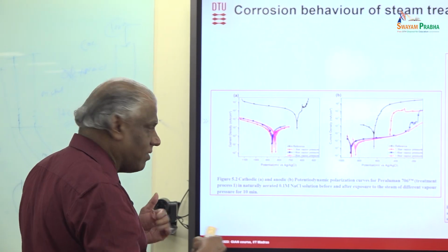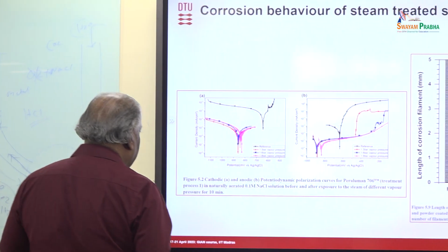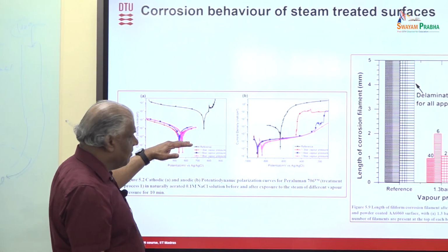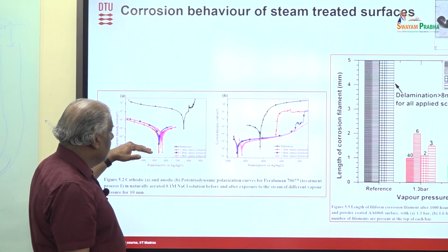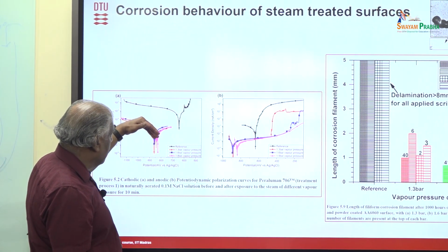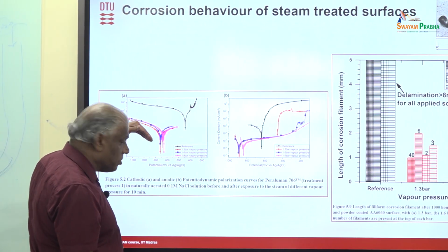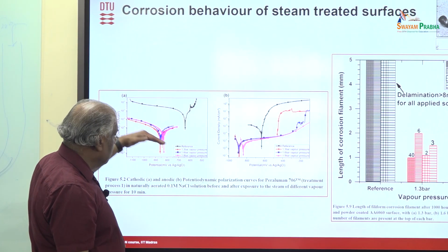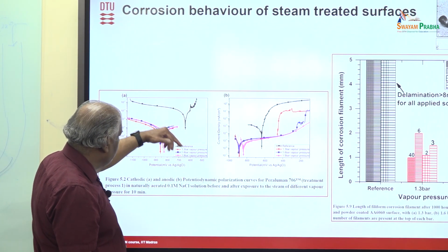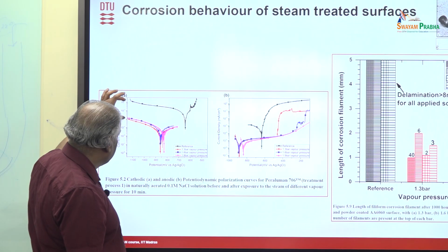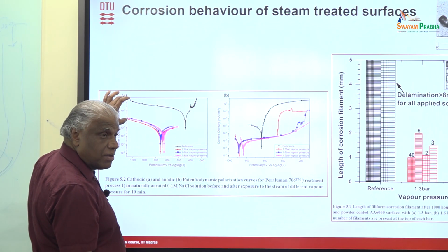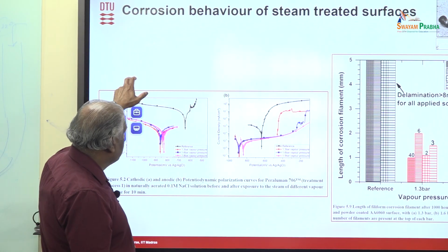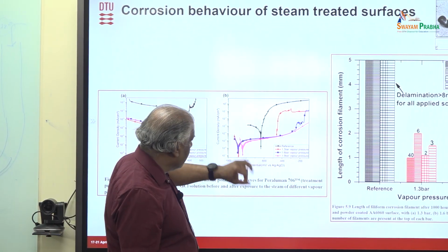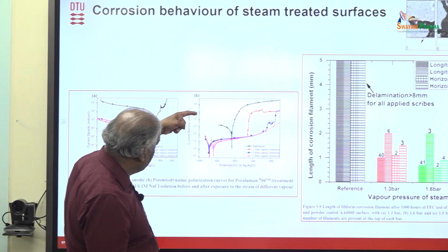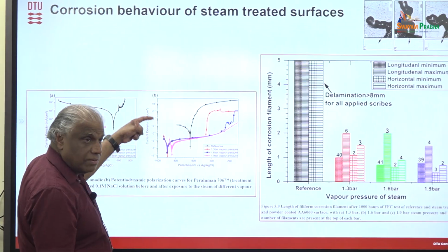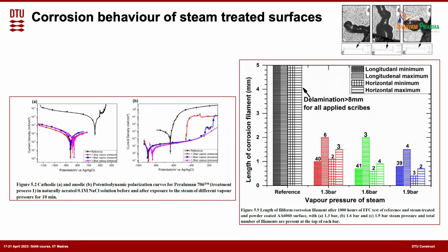I'm just jumping from one result to another. But you can see that all this coating works very well. You can see that the cathodic reactivity is reduced so much. This is without coating, and with coating the cathodic reactivity is reduced at least 100 times. If you look here, you can also see that the anodic reactivity is reduced so much, maybe more than 4 decades. 10,000 times the anodic reactivity is decreased.